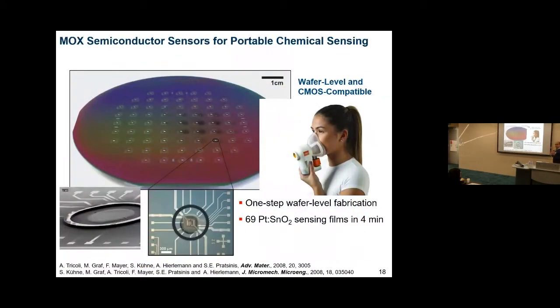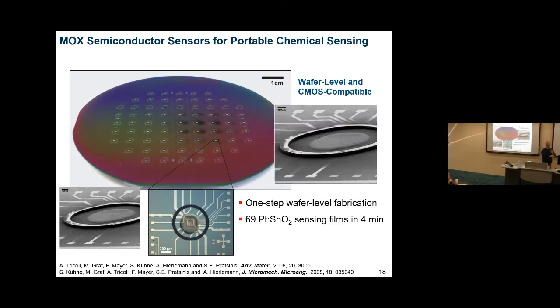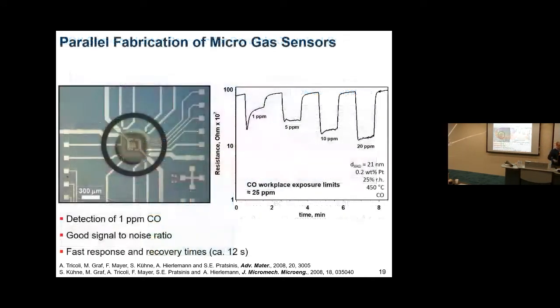Now I'm going to go to the detection. A few years ago, quite a long time ago, we worked on developing methods to produce chemoresistive metal-oxide sensors on wafers. We worked with companies like Sensirion, and we demonstrated that you can deposit this sensing layer on large area wafers with a short process. And then we tried to utilize this material for chemical sensing.